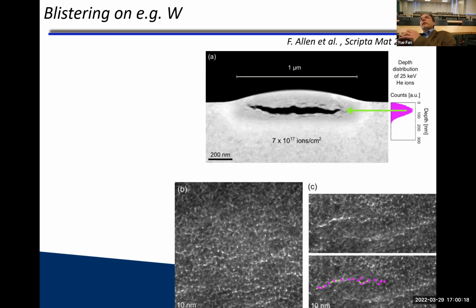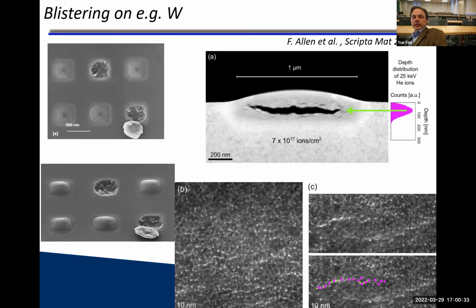Therefore, the surface to volume ratio is different, and that leads to the expansion that drives this blistering effect. You can see very nicely how the helium bubbles start connecting and ultimately form these initial critical cracks. And it can be so bad that the whole blisters just simply pop out.